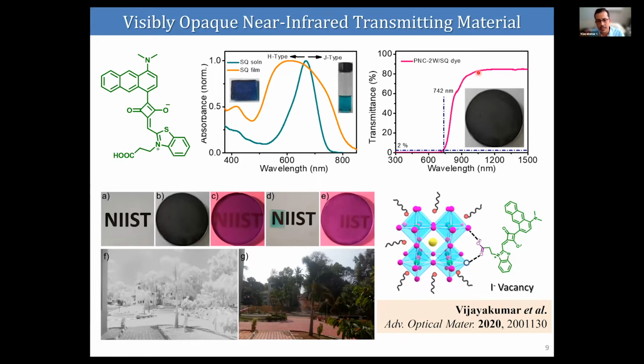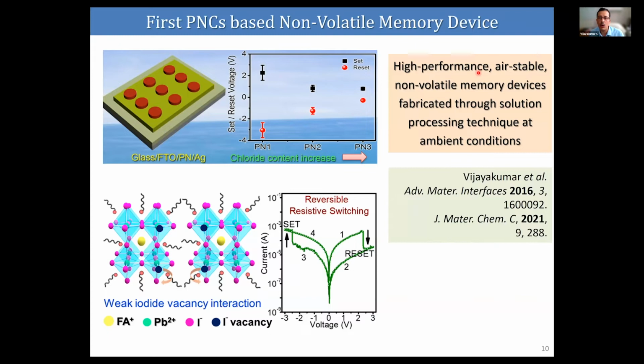And several of our nanocrystals are suitable for making non-volatile memory devices. And we found that the iodide ion vacancies in these materials play a key role, and the switching basically depends on the migration of these iodide ion vacancies from one electrode to another. And we developed several high-performance, air-stable, non-volatile memory devices, of course, with the help of collaborators. My collaborators in NIIST made the devices. We are basically chemistry people. And we made these devices by solution processing under ambient conditions. And it is possible to tune the entire memory properties by chemically modifying the structure, by adding chloride ion to the material. It is possible to switch the set and reset voltages.